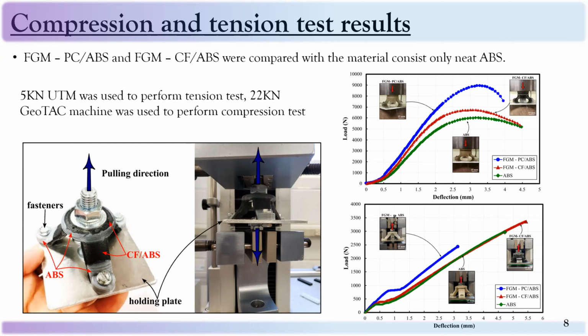And in the second image, you see the part under tension loads. Here, the FGM fiber reinforced ABS component demonstrated higher strength than other components because the strength of neat ABS was increased by incorporating short carbon fibers into high stress concentration areas. Overall, the results show that FGMs fabricated by the FFF, a low-cost process, inherited strength, stiffness, and toughness, which showed an improvement of overall material properties in comparison with the neat ABS materials.